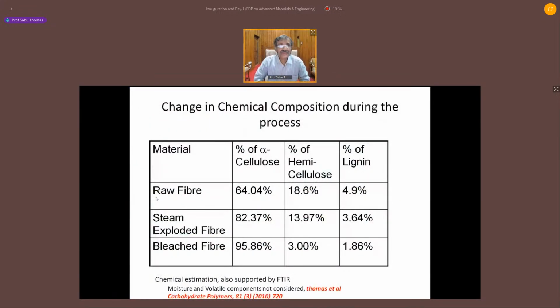Let me also show you the dynamics of the enrichment process. What happens at each stage? When my PhD students collect raw banana fiber from the plantation, you see the raw fiber has a cellulose content of 64%, hemicellulose 18.6%, and lignin 4.9%. When we do the steam explosion process, acid washing and bleaching, after the steam explosion process, the cellulose content is increased to 82.37, and you see the hemicellulose is decreased, lignin is sort of washed away. When you continue the process and after the bleaching, you get a material which has a high content of cellulose, nanocellulose. My PhD student produced up to 98% of nanocellulose.